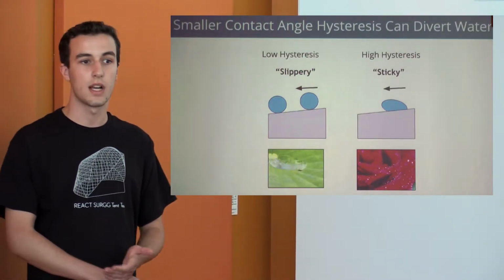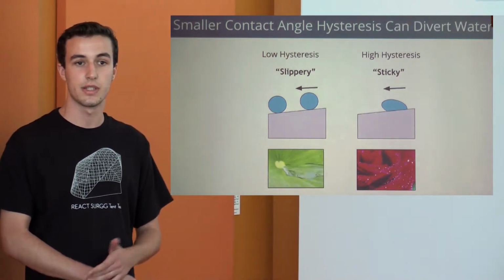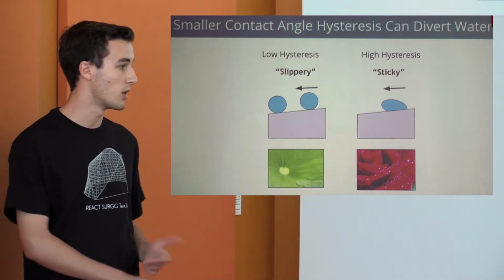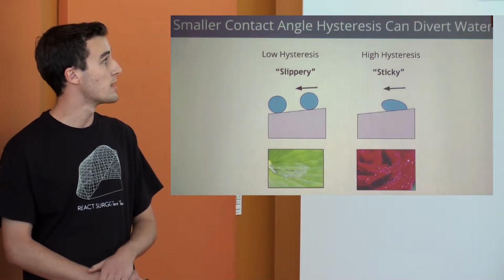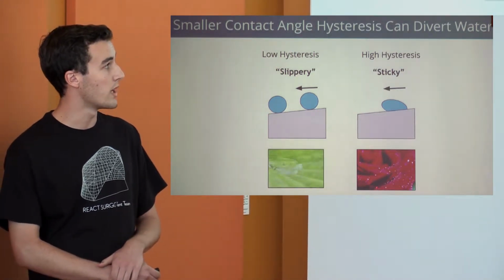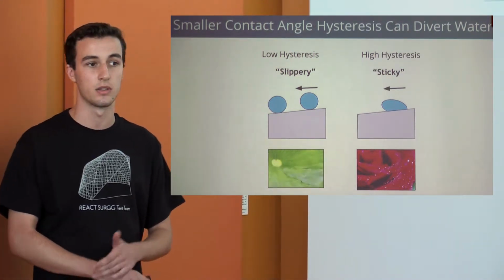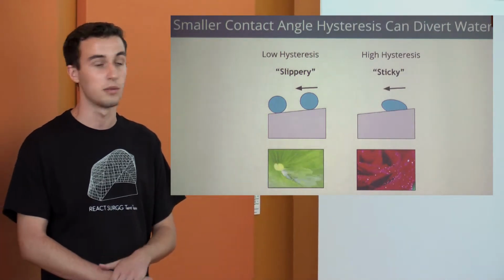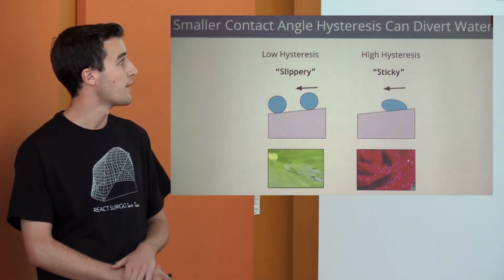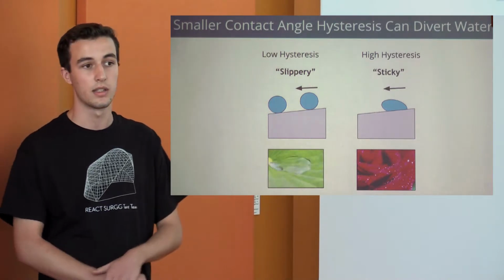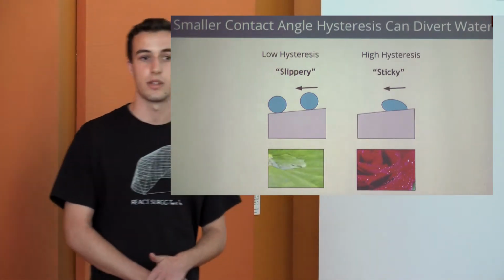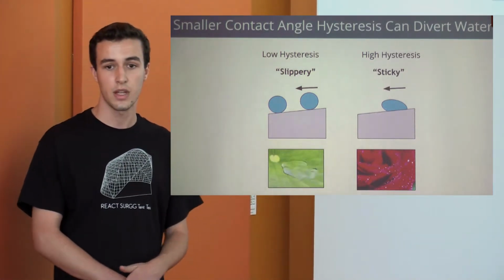However, just because you have a contact angle greater than 150 degrees does not necessarily mean that it will work for our situation. It's possible, for instance, with a rose petal to have a contact angle that seems to be superhydrophobic, but the surface is sticky. We wanted a slippery surface like the lotus leaf. So we measured this through something called contact angle hysteresis.